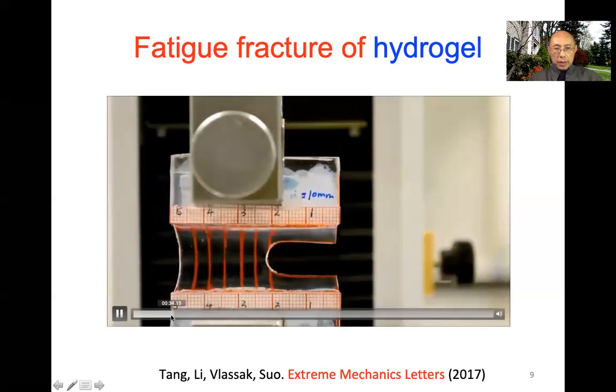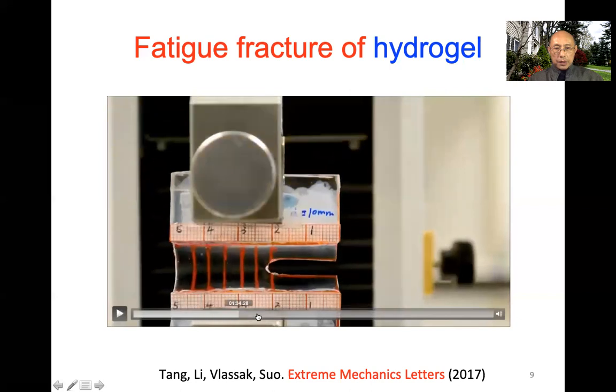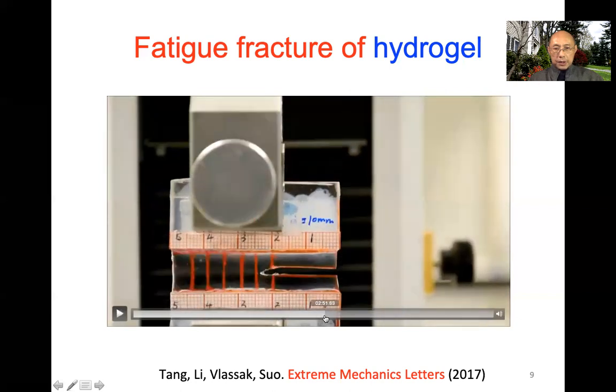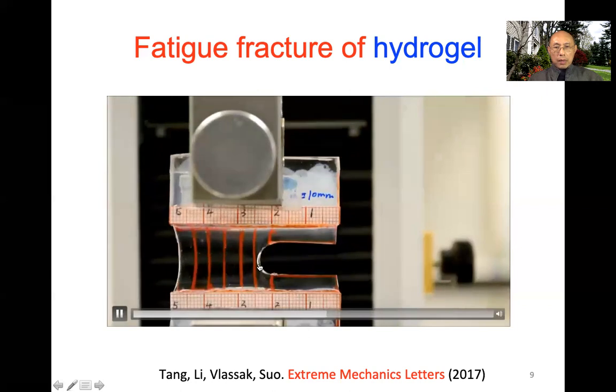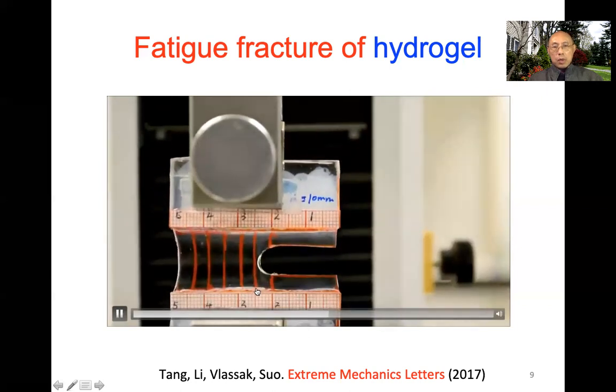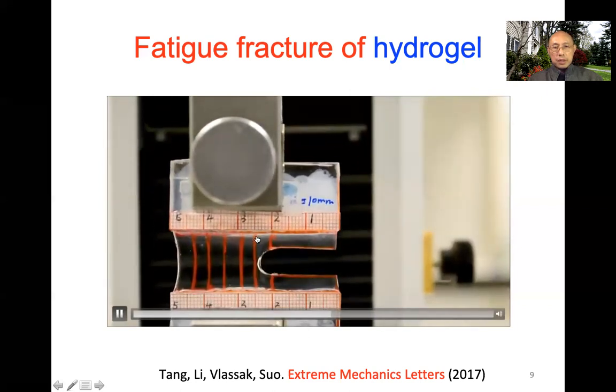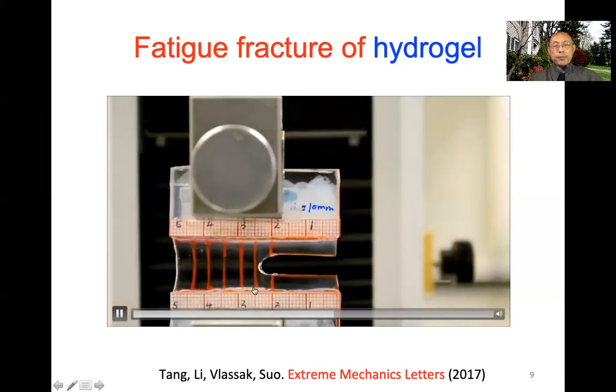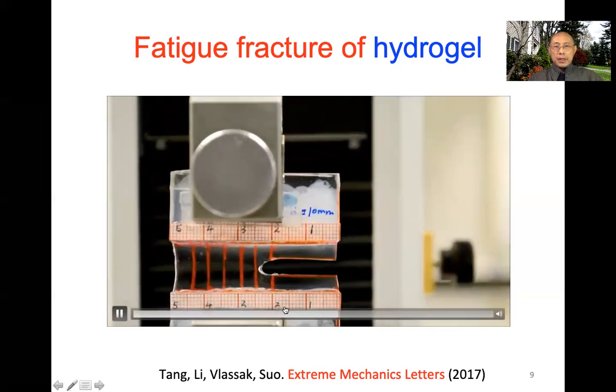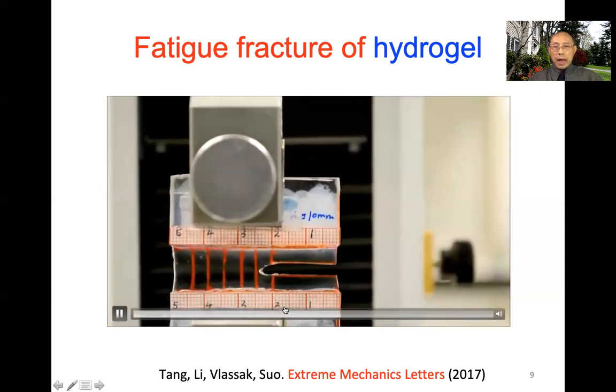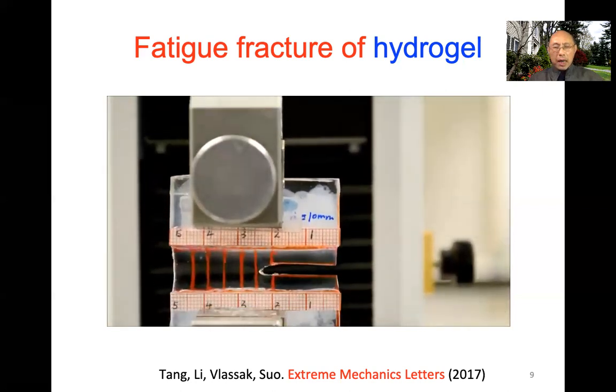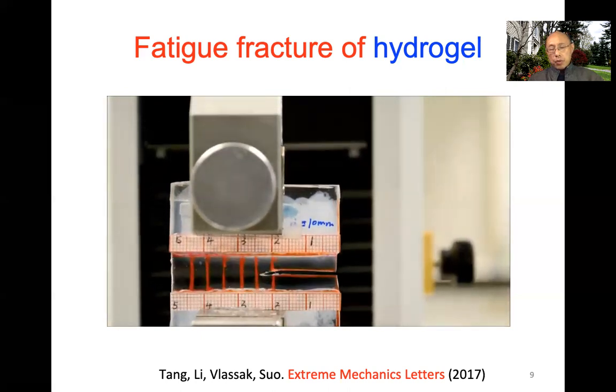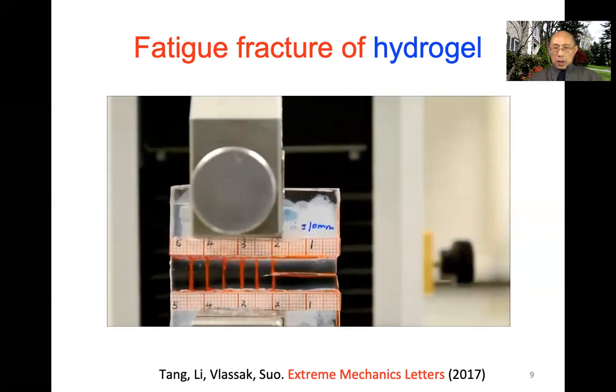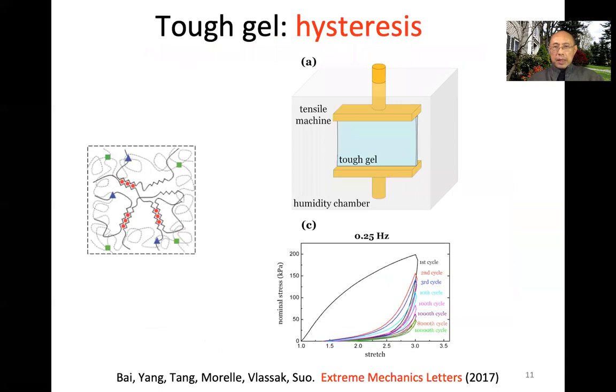The crack doesn't look like it's growing, but it does grow slowly. Let me accelerate this video. So you can see after some cycles, the crack has already grown near to the second red mark. Even for this very elastic polyacrylamide gel, it suffers fatigue crack growth. So we try to study this mechanism.